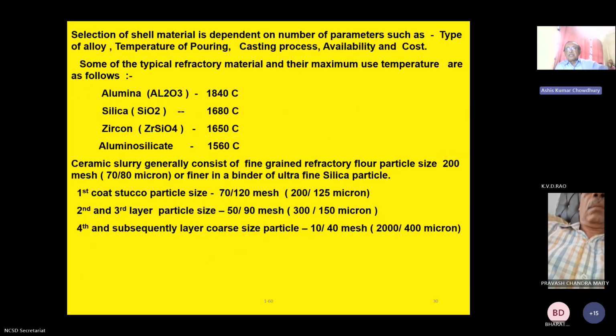Selection of shell material is dependent on a number of parameters such as type of alloy, temperature of pouring, casting process, and availability and cost. Some of the typical refractory materials and their maximum use temperature are: alumina can be used up to 1840, silica 1680 degrees centigrade, zircon up to 1650 degrees centigrade, aluminosilicate 1560.